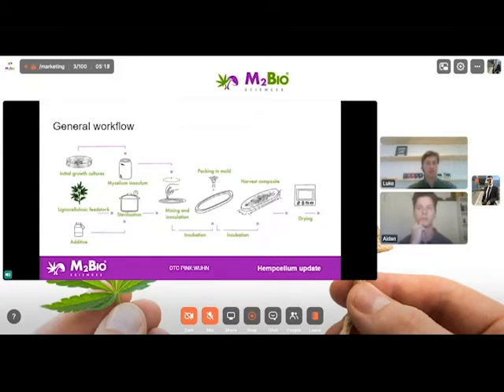We then mix the sterilized substrate with the mycelium and then add it to the mold so that the mycelium can grow through the substrate in the mold, removing it from the mold to allow the aerial hyphae to grow for a short while before baking it and creating the preferred surface we want for our mushroom packaging products.